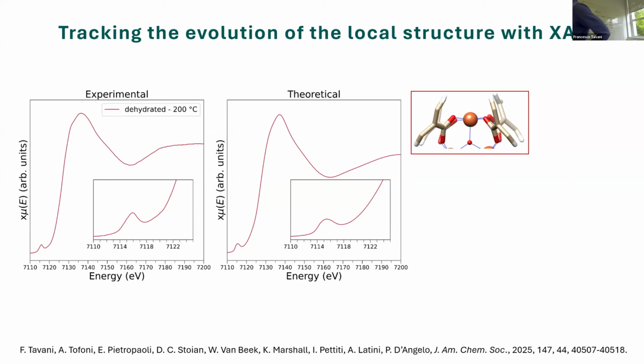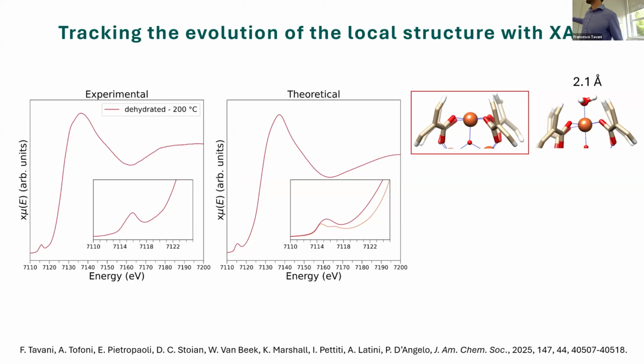Then you have a comparison of a theoretical curve calculated from a model where all trimeric units bear the iron sites in a square pyramidal configuration. You can see that there's a single transition in the pre-edge region. At this point, we computationally add one water molecule per iron site, actually 2 water molecules per trimer. You can see that the theoretical calculation shows the presence of 2 peaks because we are going from a square pyramidal to an octahedral configuration. Then we keep increasing, always computationally, the water loading in the MOF, and we calculate the corresponding XANES.